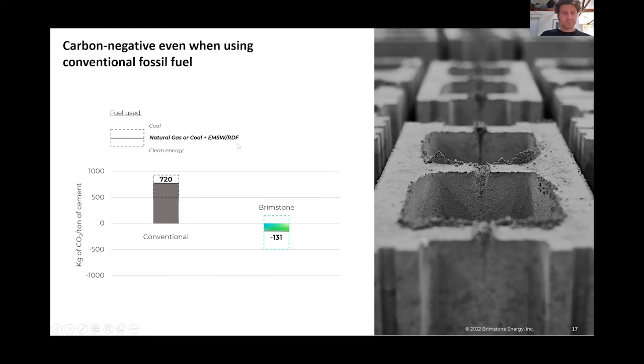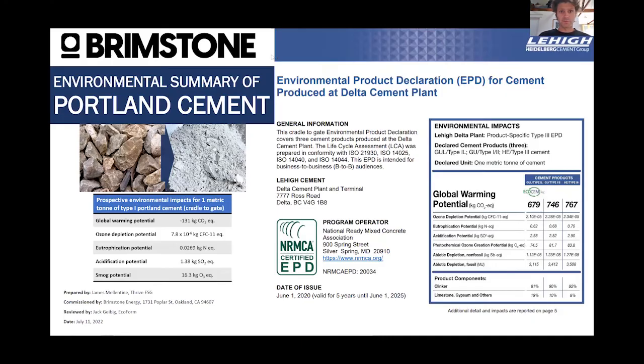But you don't actually have to believe me. For the first time I'm sharing, earlier this month we had a third party do an LCA, a life cycle emissions analysis, on our process, following the ISO standard, the same standard that's used for environmental product declarations. And they found that our global warming potential was minus 131 kilograms of CO2 per ton of Portland cement, using a conventional mix of coal and refuse derived fuel.